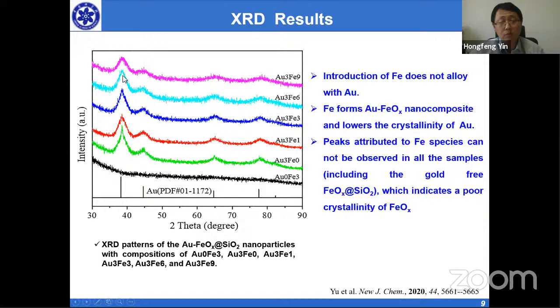Also from the XRD, we cannot observe only an iron-gold alloy peak or only an iron oxide peak. So the introduction of iron does not alloy with gold. With the forming of the gold iron oxide composite, the gold crystallinity will be reduced.